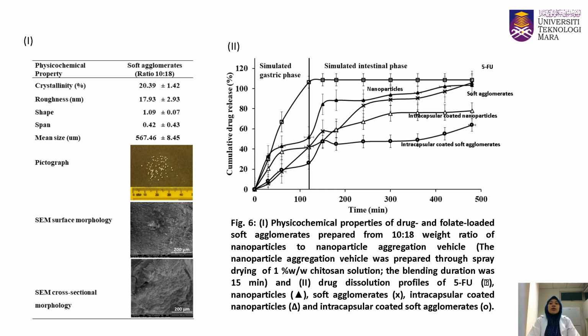Here I wish to show you the drug release data. The drug release study is conducted using a transitional design, whereby we conducted the drug release study for the first 2 hours in the simulated gastric phase, followed by the subsequent hours in simulated intestinal fluid. You can see that the pure drug is released relatively fast in gastric fluid. The same goes for nanoparticles. However, formulating nanoparticles into soft agglomerates reduces the specific surface area, and as a result, you can see a lower drug release propensity taking place.